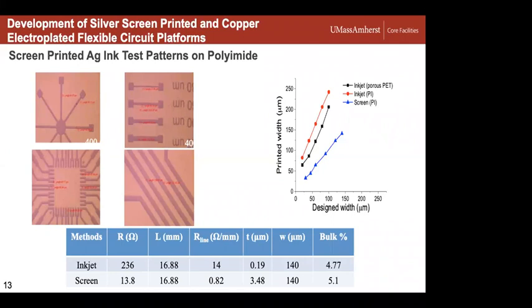With the screen printed, you're starting at about 1 to 2 microns, and you can get up to, I think we've demonstrated about 6 to 8 microns, and certainly if you're doing it right, you can get up towards 25 microns, depending on ink viscosity, surface parameters of the substrate, as well as other aspects of the printing screen and so on. So there are some benefits to that, but again, there's always something you have to watch out for or misinterpret as you look for these benefits.